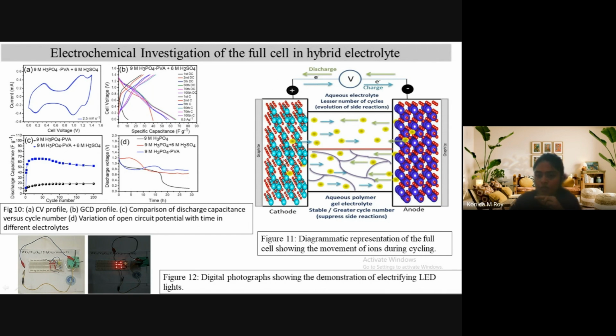Ions are moving from the anode towards the cathode, and to balance out, the electrons are moving from the negative towards positive. And in the charging mode, what is happening? The ions are coming out of the cathode and moving towards the anode. So here a side reaction is occurring, so after a few cycles, we cannot move forward. But in the cross-linking polymer, we can see that the ions are trapped and side reactions are not happening because it is reducing the water solvation.